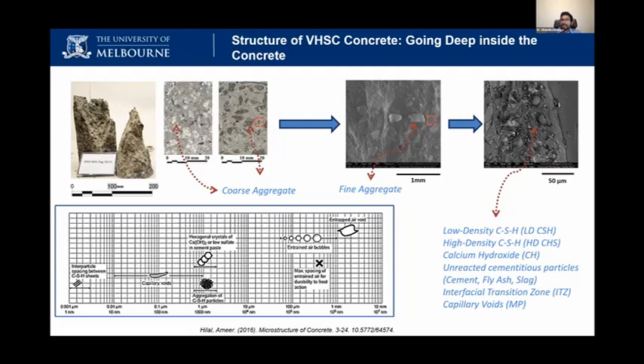And there were a lot of parameters, a lot of types of aggregate sizes and different types of sand, and they used different types of silica fumes, ultra fine silica fumes, and fly ash from different sources, because Australia has a lot of coal power plants, so they sourced fly ash from different power plants. But finally, they found the Gladstone fly ash, from the coal power plant in the Gladstone area, is suitable, and also slag. Also the same, they tried slag from different suppliers. It was quite a strenuous, difficult, time consuming, costly process.